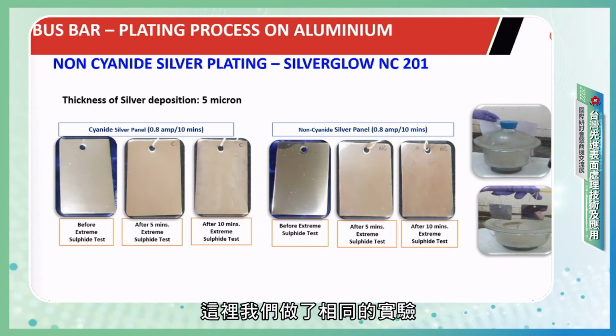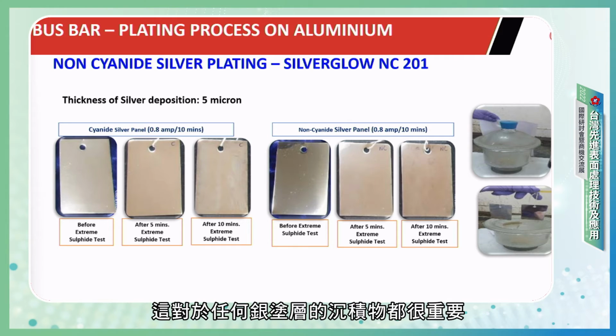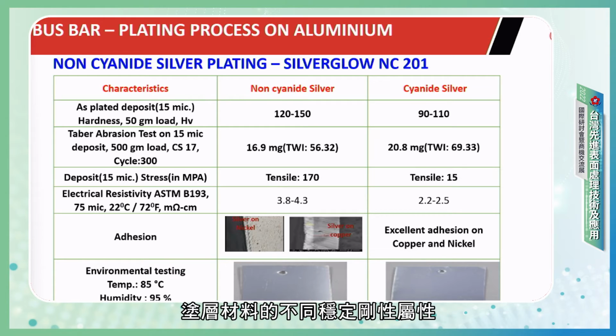Now let's see the second one. Here we have done the same experiment, but in this case we kept the components in a desiccator with saturated sulfide solution in the bottom, so the atmosphere remains with more sulfur. We saw that cyanide and non-cyanide don't have much of an issue. So what we're trying to say is, as I mentioned in the introduction, our process behaves almost like cyanide in terms of tarnishing resistance, which is important for any deposited silver coating. This will give us an idea about different tribological properties of the coated materials.